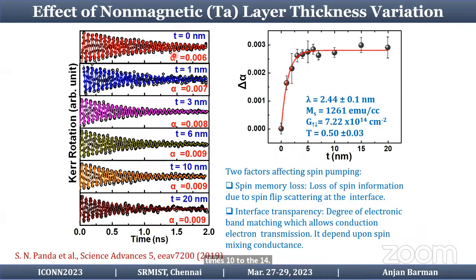And this is the non-magnetic layer thickness dependence. Here you can see the variation of delta alpha as a function of t, which increases and then saturates. From here, we find the spin diffusion length in tantalum to be 2.44 nanometer, and the spin transparency to be 0.5, or 50% of the spin current will be transported to the non-magnet.